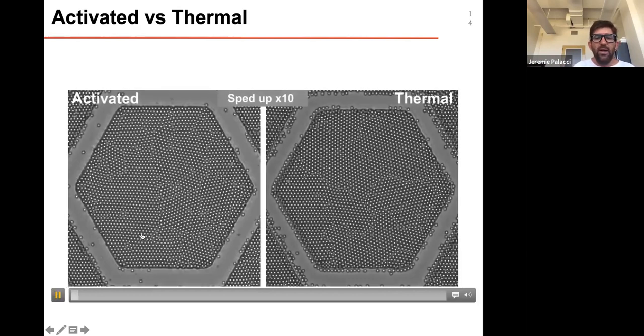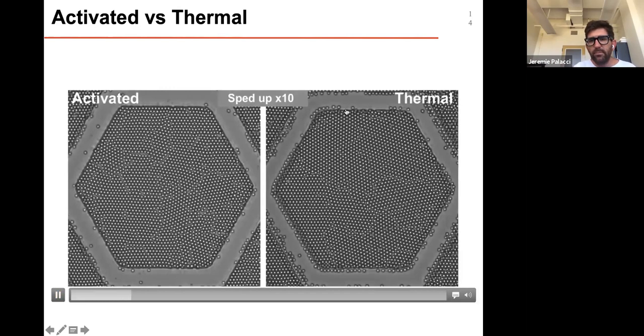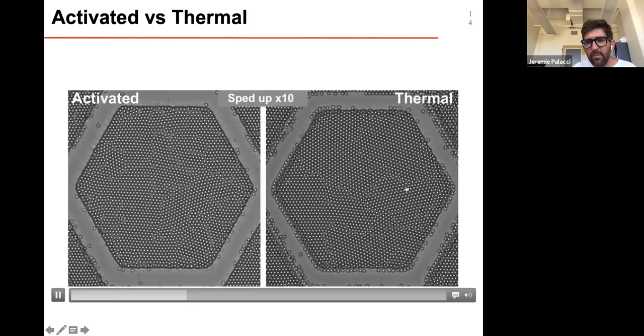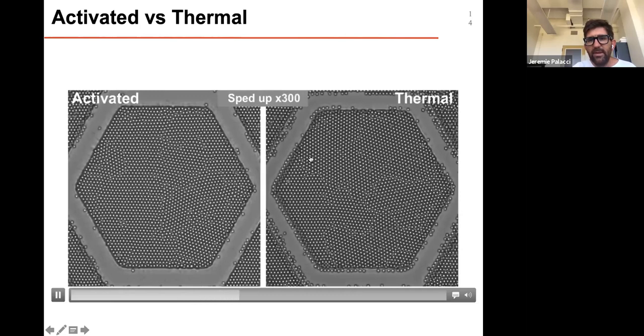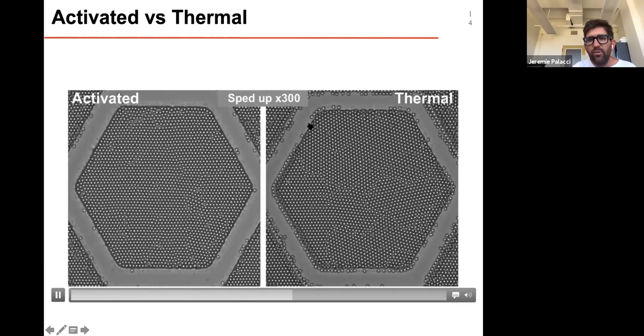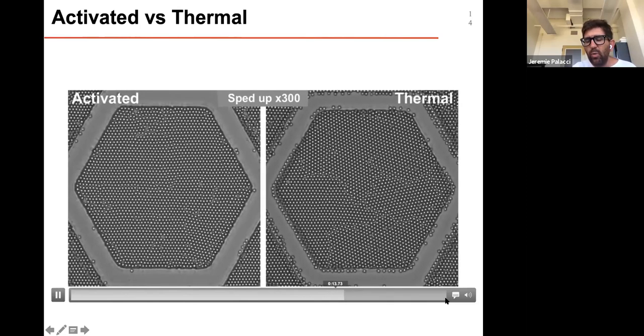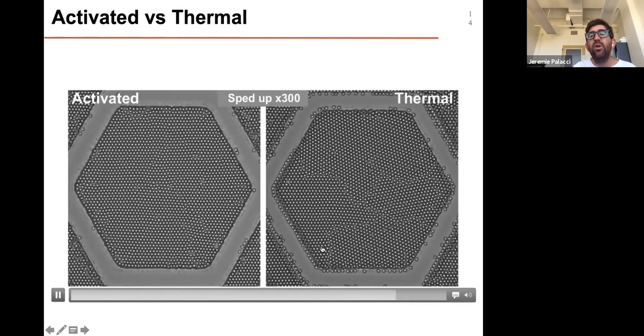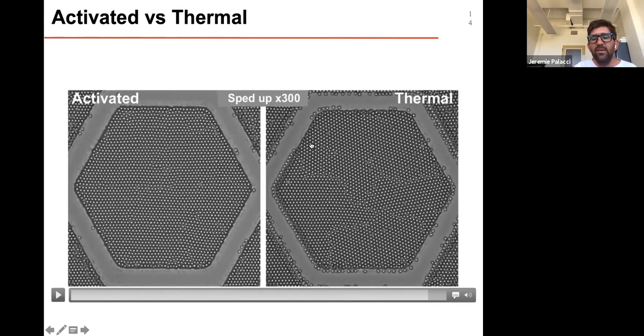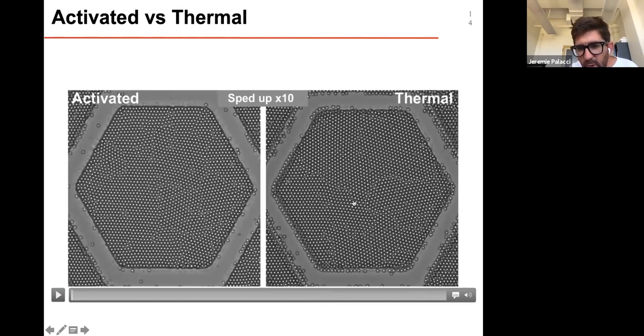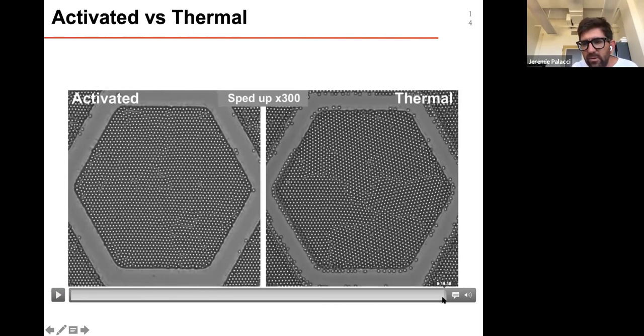At first, let's look at the thermal case. You see very little happens. Now it's sped up 10 times. And if you speed up even 300 times, you see that there's barely any change within the course of this experiment. This movie is 45 minutes. The bottom line is that if we take this system and let it evolve over 45 minutes, we barely see any change. We initially started with a variety of grains of crystal separated by grain boundaries. After 45 minutes, we have some change, a few of those grains changed, but we still have a bunch of crystallites separated by grain boundaries.